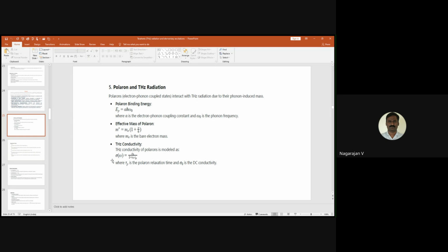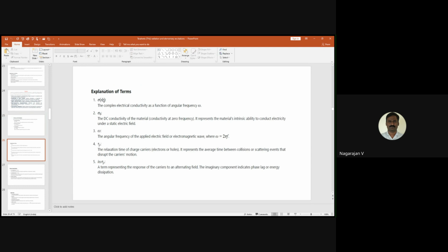Terahertz conductivity is represented as sigma of omega equals sigma naught over 1 plus i omega tau p. Here tau p is the polaron relaxation time, and sigma naught is the DC conductivity. Sigma of omega is the complex electrical conductivity as a function of angular frequency omega. Sigma naught is the conductivity of the material, which represents the material's intrinsic ability to conduct electricity in a static electric field. Omega is the angular frequency of the applied electric field of the electromagnetic wave, omega equals 2 pi f.